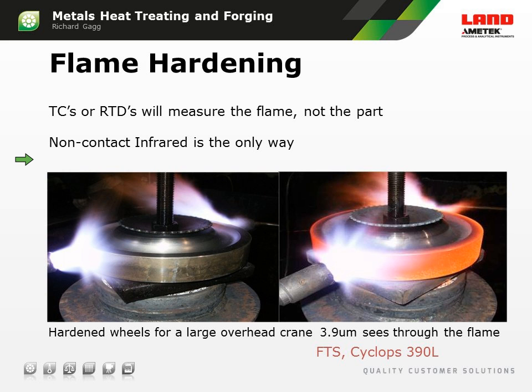Now, it might seem obvious, but if you want to measure the surface of that material when it's being flame hardened, you can't use a thermocouple or any other contact device, because that thermocouple is sitting in the flame and getting heated by the flame, and it's not measuring the temperature of the surface of the material. In this particular case, if we use a 3.9 micrometer waveband non-contact thermometer, like an FTS or a Cyclops 390L, then we see through that flame. That flame is not seen at all, not measured at all, and we see directly the surface that is being heated. So this is the only way to accurately measure that temperature. Again, they will not be trying to use thermocouples because they cannot work in this application.